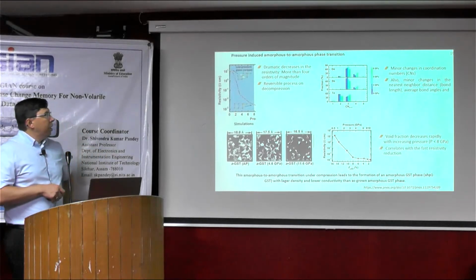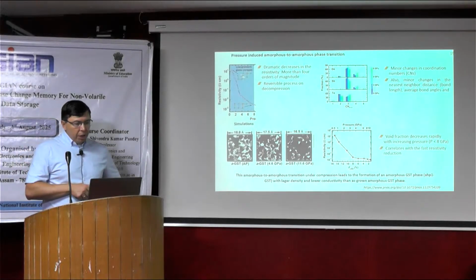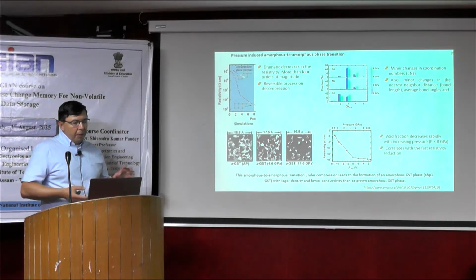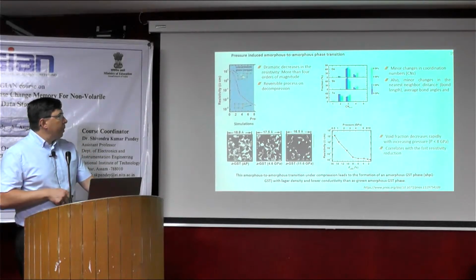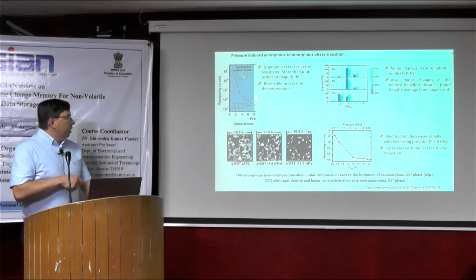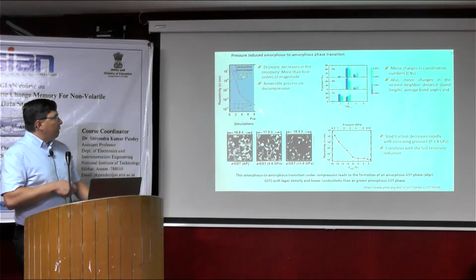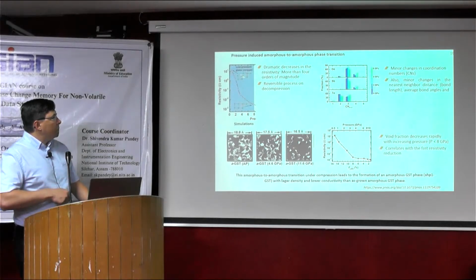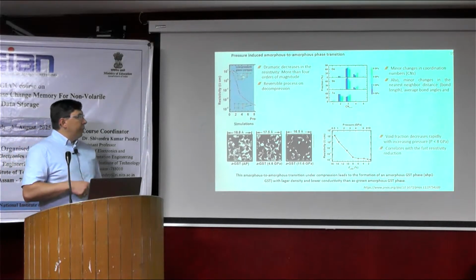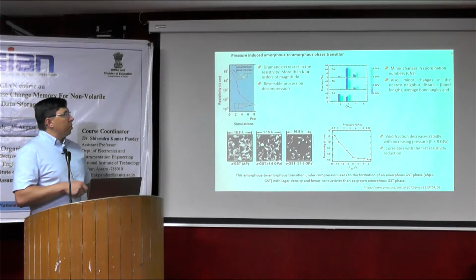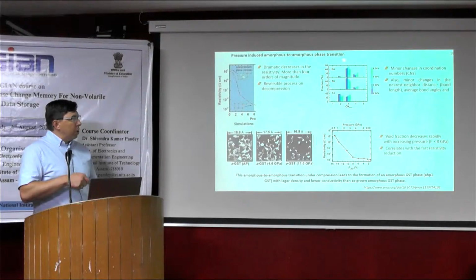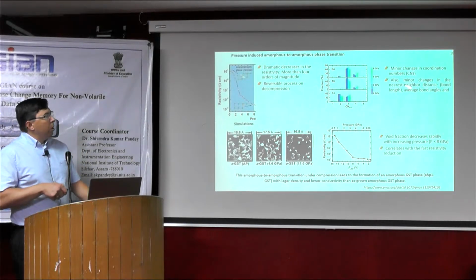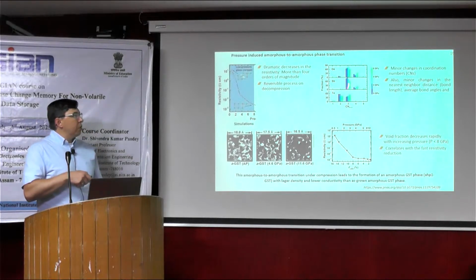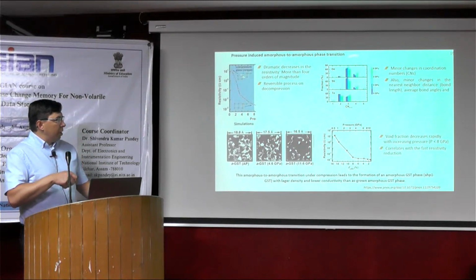So now let's look at the pressure-induced amorphous to amorphous phase change. If we press, let's say, the amorphous phase up to 8 gigapascal, we can see a drastic change of the resistivity here. This is several orders of magnitude, so it's decreasing. But this is a reversible process. During this process, there is a minor change in coordination number, and also minor changes in the nearest neighbor distance. The average bond length also stays almost the same.